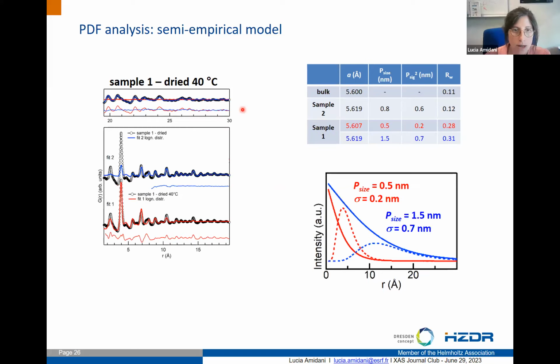So if then I go and say, okay, let's do the fit starting from a bit less than 1 nanometer, I'm getting a very nice fit of the higher oscillations, and I get a peak at 1.5 nanometers. I get a totally different distribution, but I miss completely the first peak.